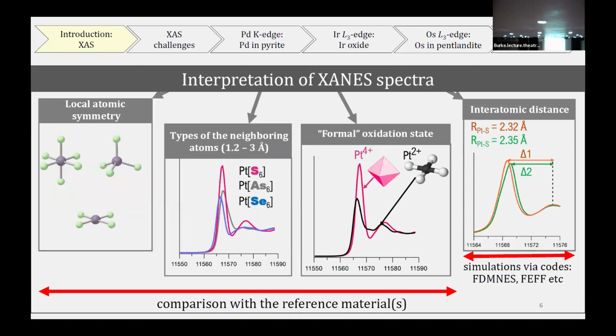And XANES is an extremely informative part of the spectrum. Through comparison with the standards, we can get information on the local atomic symmetry. For example, we can discriminate between octahedral and tetrahedral states. But the coolest thing is that we can also discriminate between different geometries, even if the coordination number is the same. For example, we can distinguish between tetrahedral and square planar symmetry. Then, in case we have similar polyhedra surrounding the absorbing atom, but the sort of the atom is different, we can also discriminate between those states.